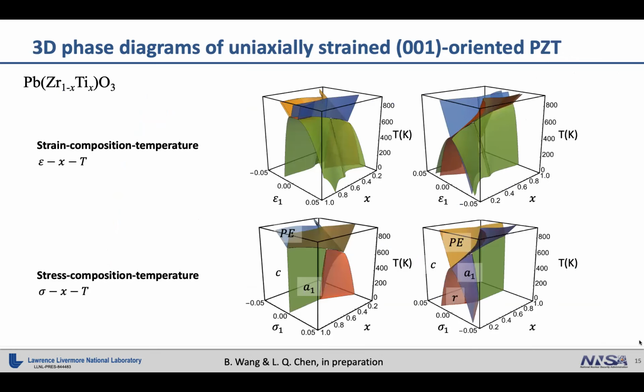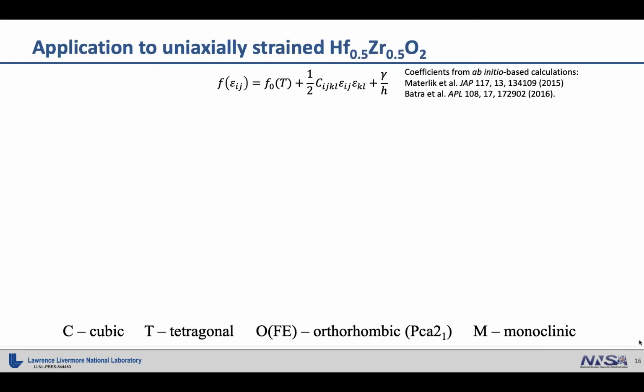Okay, we also applied it to a second example, which is PZT. For simplicity, we just consider a 1D strain case, and we just consider the rhombohedral and tetragonal phases, without considering the antiferroelectric phase on the rhombohedral side, the PZO side. But with this simple model, we can also obtain the analytical expression for all of the phase boundaries. And we can identify the critical lines, where first order becomes second order, and also the triple points, where there is three-phase coexistence. And when the two merge, they give us the tricritical point.